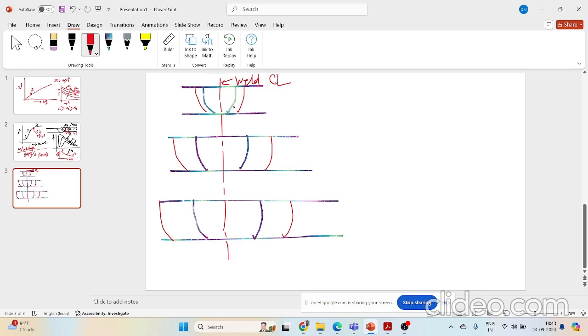Now, this is location 1 in the heat affected zone. This is location 2 in the heat affected zone. And this is location 3 in the heat affected zone. So as I am moving downwards, what is happening? I am increasing my heat input per unit length. Q by V is getting increased. And as I was saying, as you increase your Q by V, the ratio of total heat input to the welding speed, the size of your heat affected zone will increase, right?